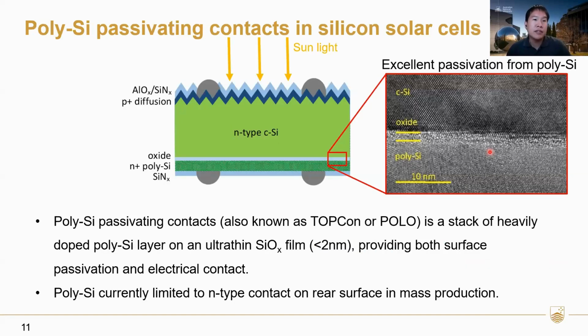So I've mentioned passivating contacts here previously, and this is a big part of the talk as well. We'll mainly be focusing on polysilicon passivating contacts. It's sometimes also known as TOPCon or POLO. Essentially what it is, if you look at the TEM image here, we have a layer of polysilicon at the bottom. This is heavily doped, typically up to about 1E20 to 3E20 in that range. And this polysilicon sits on top of a very thin oxide, typically about 1.5 to 2 nanometers. By having that interfacial oxide separating the crystalline silicon and polysilicon, this structure provides both surface passivation and good electrical contact, typically through tunneling effects, either that or pinholes in the oxide.